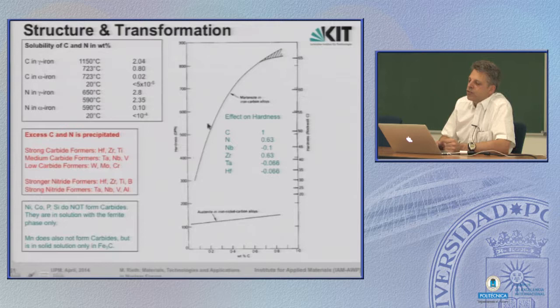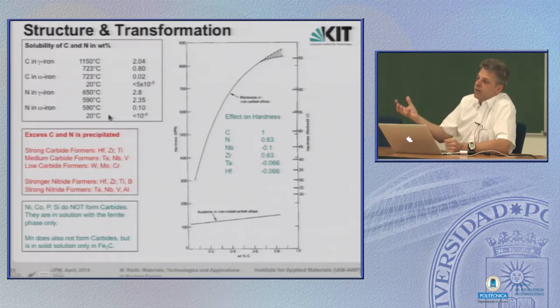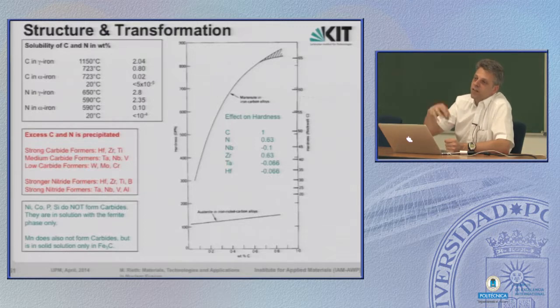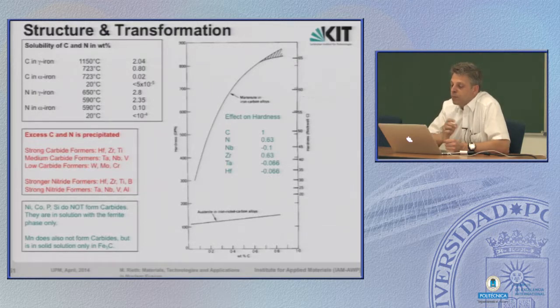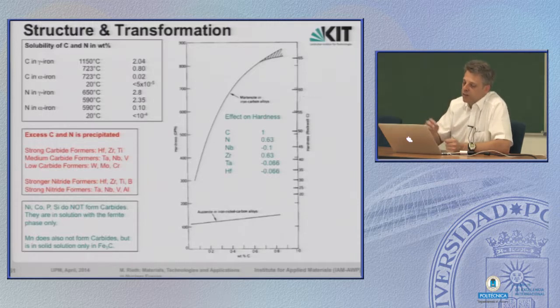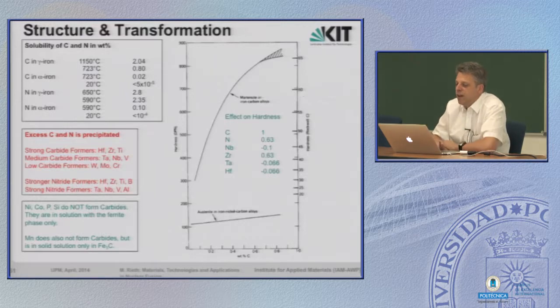Here is the answer to the question, what happens to the carbon in the martensite? Here are again some solubility limits of carbon for different structures. This I have already mentioned. So if the austenite phase transfers into the ferritic martensitic phase, the carbon is first captured because in general it's not soluble anymore, but it has been captured in the lattice, and during tempering it has to diffuse somewhere. During this diffusion, it combines often with elements which attract carbon.